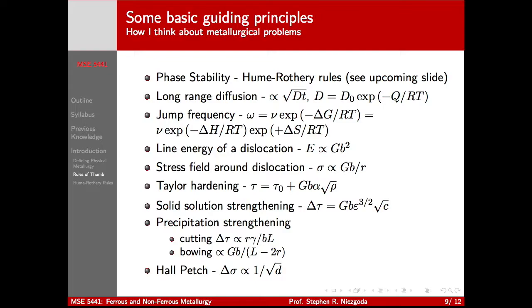The line energy of a dislocation. Everyone should be able to pop off Gb squared. That should be something you've learned in structure and defects and mechanical behavior, seen many, many times. How does the stress field around the dislocation decay? As 1 over the distance, and it's proportional to the shear modulus of your material and the extent of the Burgers vector. Why the extent of the Burgers vector? Because that's how big your lattice distortion is.